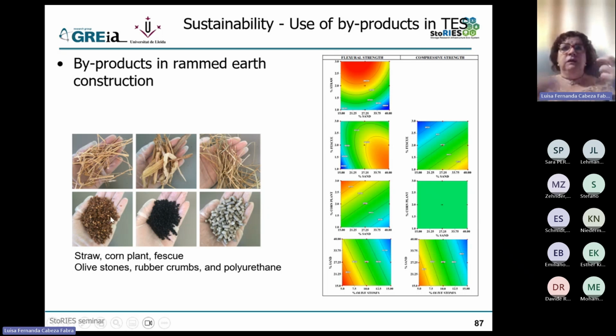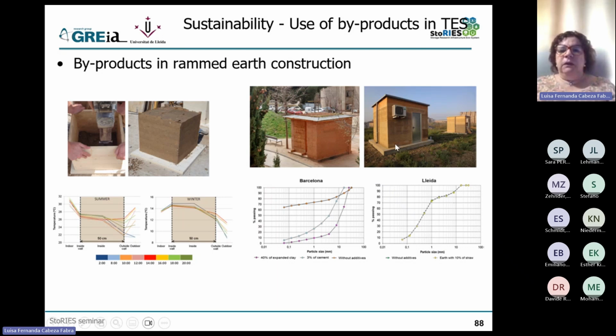One is olive stones, which is what is produced as a waste from producing olive oil. Rubber crumbs, which is a waste from tires, from the cars. And this polyurethane, which is actually a waste from recycling refrigerators. All our refrigerators have an insulation around them, which is polyurethane based. And when they recycle it, this type of pellets is what comes from the recycling. Again, we tested it. We did this also in these cubicles. I don't want to go into detail, but here again, it's based on sensible performance, but trying to get also this thermal inertia effect in the building.